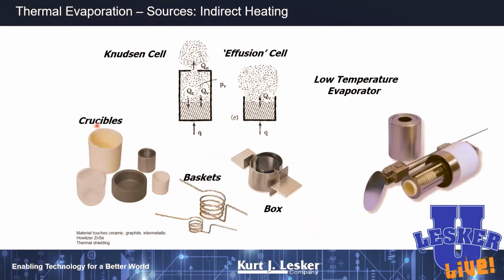If you want to try to make a thicker film, we can graduate to crucibles, or if you don't like to reload your system after every deposition, we can use a crucible. But now we've added a thermal interface. So the crucible itself sits inside a basket. So now we have a thermal interface between the basket and the crucible, and then the crucible and your source material that goes on the inside. And your crucibles can be things like aluminum oxide, silicon dioxide, pyrolytic graphite, metals like tungsten or copper, boron nitride if you don't want your material to stick very much.